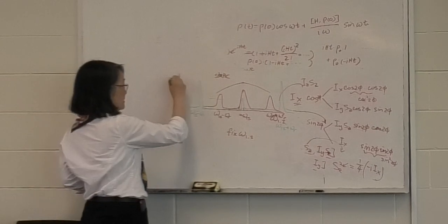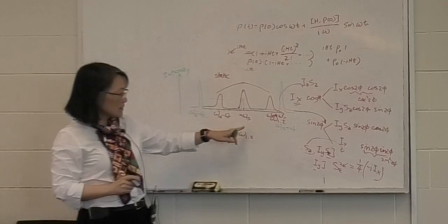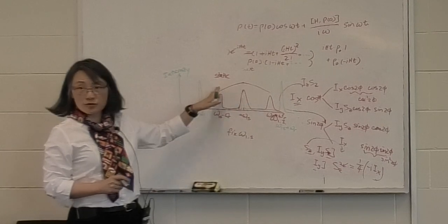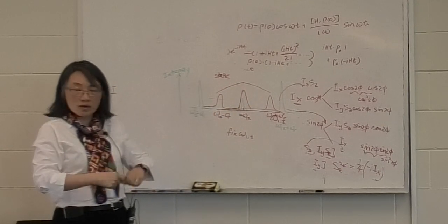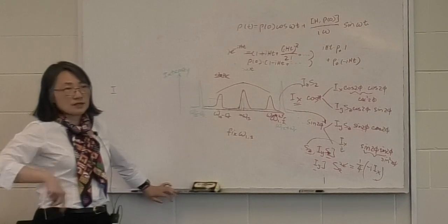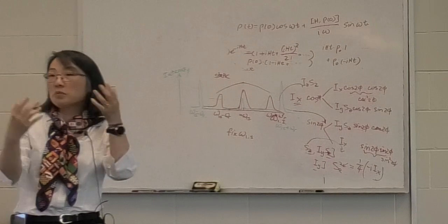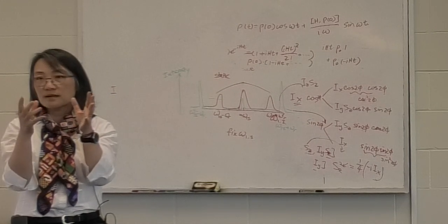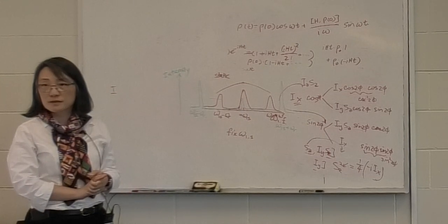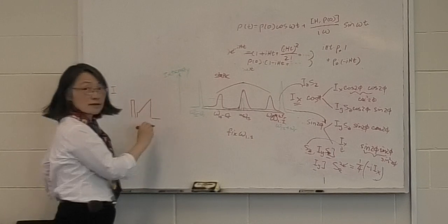So what is the y-axis? It's the intensity of the signal you're looking at, the S-spin signal. You get better CP transfer by going off to the sideband matching instead of the Hartmann-Hahn omega-1S situation. But in the static situation, it works over a fairly broad range. And I think if you want to prove that, you can probably write down, because the way we prove the Hartmann-Hahn matching and CP, we say I have this wonderful omega-1 squared term. But if omega-1I or omega-1S is slightly different, it still works to some extent, just not perfect. So ramp CP is for a practical purpose. A steep ramp doesn't work because then you spend very little time being correct.